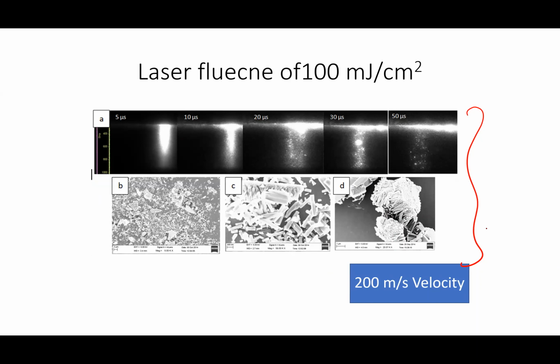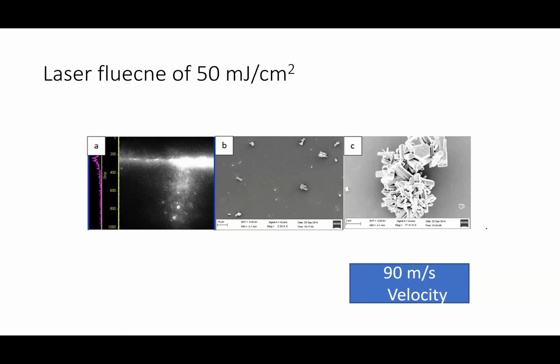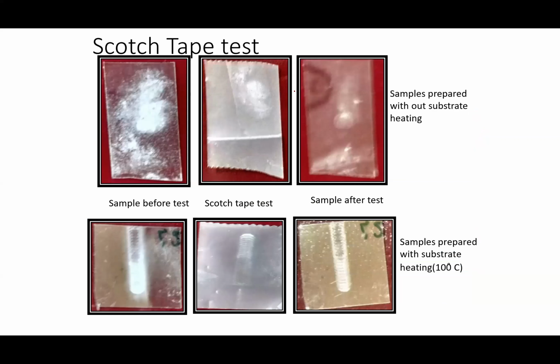This transfer can be on a large area or on a small area, based on the size of the laser we are using, and we could estimate the velocity to be around 200 meters per second. Then we slowly reduced our laser fluence to see how the particle moves. At 50 millijoule per centimeter square, where the laser fluence is low, we could see the particle just falling on the surface without any impact of the laser on the material. From this study, we understood that this is a very good system where we can transfer any kind of structure from one region to another.